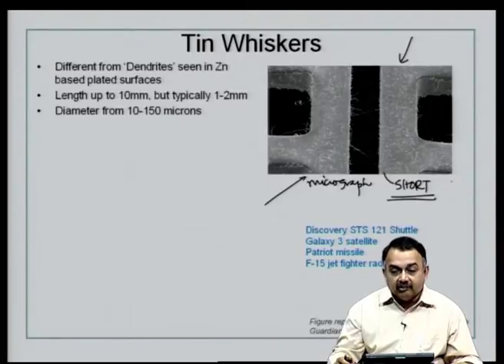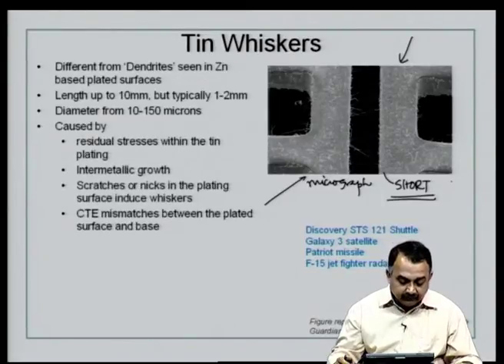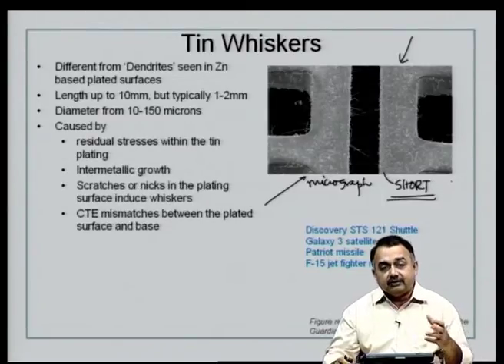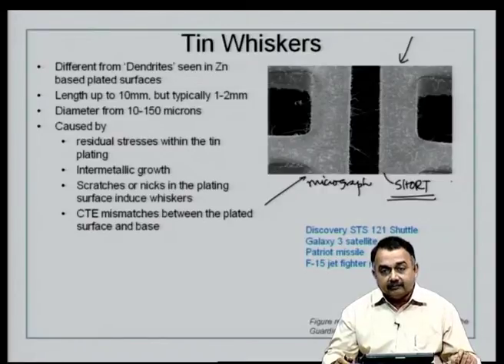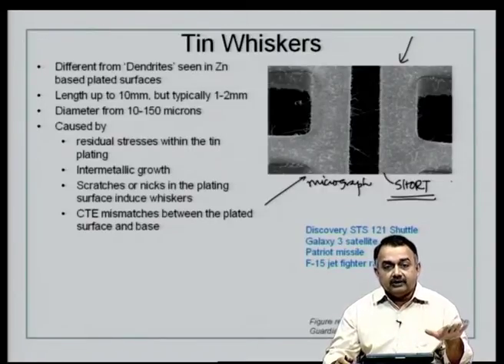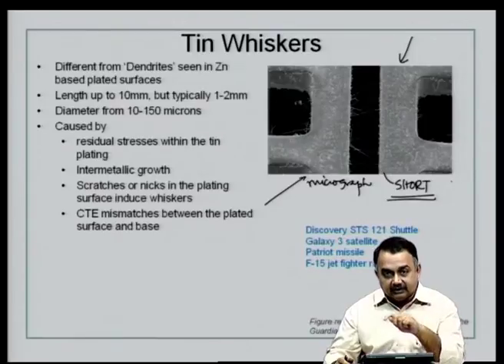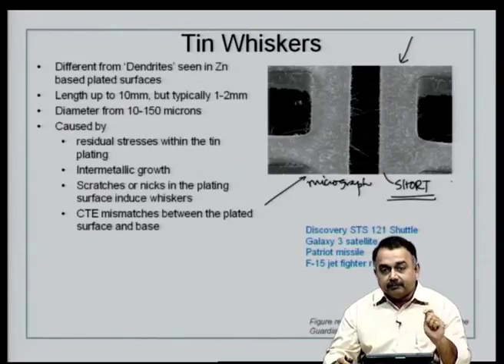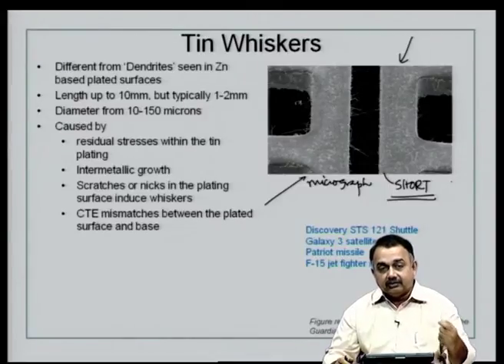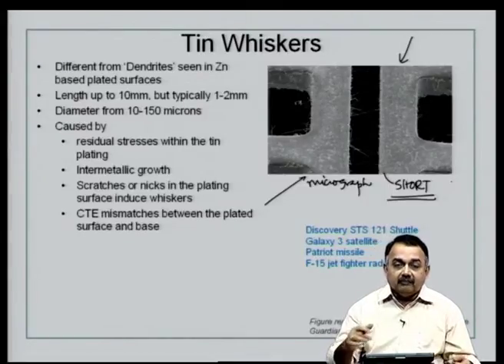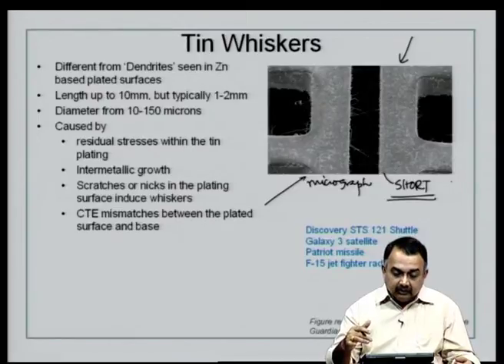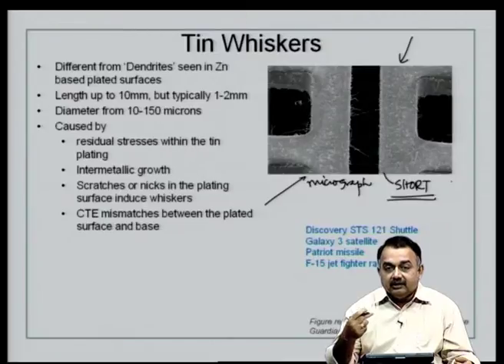The physical parameters of these tin whiskers: typically they can grow up to 10 mm, but typically about 1 to 2 mm, very fast, with diameters ranging from 10 to 150 microns. They are caused by residual stresses within the tin plating. So, in a tin plating finish, if you create a nick or a scratch post process, that will be a very good source for tin whiskers to grow, because that is an area where the stresses could be released from the tin thickness that you have plated.